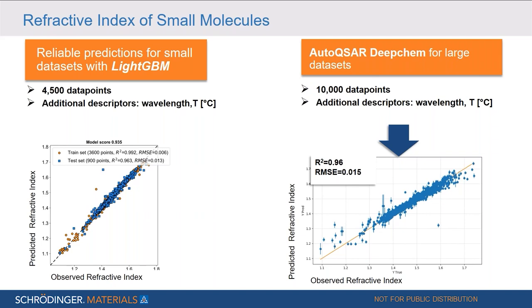And this is done here for a small and for a larger data set. And in both cases, apart from the structure, also the wavelength, namely the range from approximately 350 to 800 nanometers, and the temperature were provided as descriptors. And we see here for the small data set, the linear plot on the left-hand side, we have also very good agreement for both training and test set. So we have high R-square values and low root mean square errors. And we also see if we go to larger data sets that auto-QSAR performs very well. So just shown here on the right-hand side for 10,000 data points, we get an R-square value of 0.96. But we see also very good agreement between the observed refractive index and the predicted refractive index.